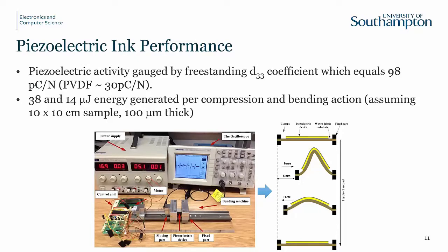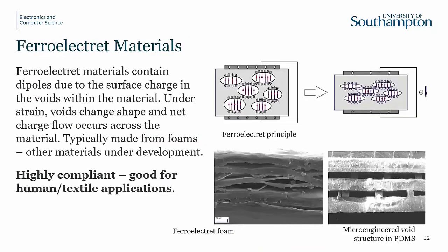And this highlights another challenge with textiles in that it doesn't couple mechanical energy into the piezoelectric film very effectively. Textiles are designed to be compliant and comfortable. That's one of the reasons why we wear them as clothes. So you don't have to put much work in to move a textile. You don't get that much energy out. So it's an obvious sort of connection there. So to improve the performance, and especially in compressive applications, we looked at ferroelectrets.